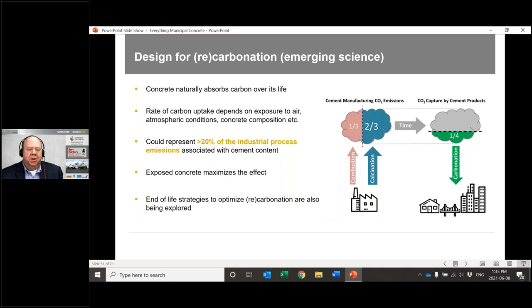Another thing we have to highlight from a technical standpoint, like we said before, when we're producing cement, we're generating CO2 from the combustion and that calcination of the limestone. But over time, concrete does absorb CO2. So we call it carbonation. It takes time. It's impacted by the surface area of the concrete. So the more surface area you have, the faster concrete absorbs CO2 from the air. But it absorbs about one quarter back over the life of the concrete. So again, from a structural standpoint, we want to be concerned about that. If we've got reinforcing steel in bridges and elements like that, we don't want to see a huge amount of carbonation because it lowers the pH of the concrete and leaves it more susceptible to corrosion.